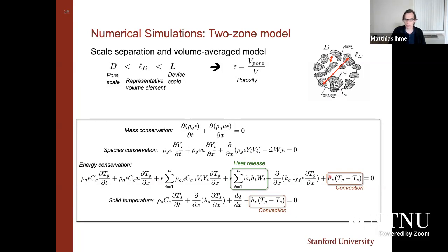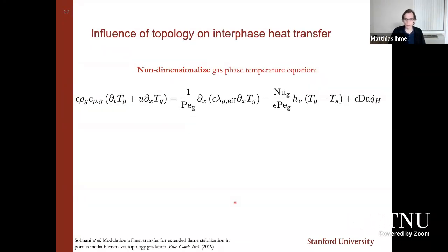This exchanges heat from the gas phase, denoted by subscript G, to the solid phase, denoted by subscript S. So we are exchanging heat between the gas phase and the solid phase. This is happening in the combustion zone, but at the same time, we are also exchanging heat from the solid phase to the gas phase in the preheat zone, right? And with this, we're coupling the solid to the gas phase just by the energy equation. And if you look closely, you also have a radiation term. This was essentially responsible for the heat losses by this glowing process, which can be quite significant for certain ceramic structures.